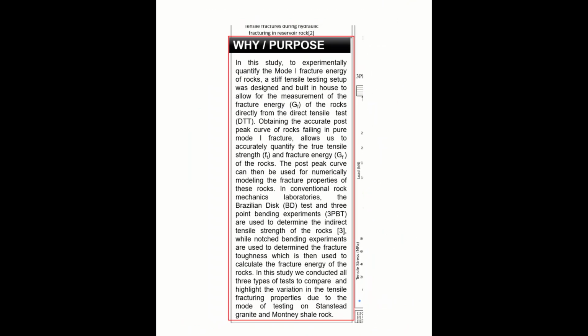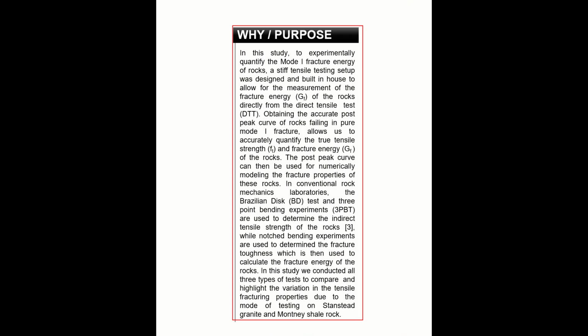Next, if we move on to the purpose of the study, in the study to experimentally quantify mode 1 fracture energy of rocks, a stiff tensile testing setup was designed and built in-house to allow for the measurement of fracture energy of rocks directly from the direct tensile test. Obtaining the accurate post-peak curve of rocks failing in pure mode 1 fracture allows us to accurately quantify the true tensile strength and fracture energy of the rocks. The post-peak curve can then be used for numerically modeling the fracturing properties of these rocks.